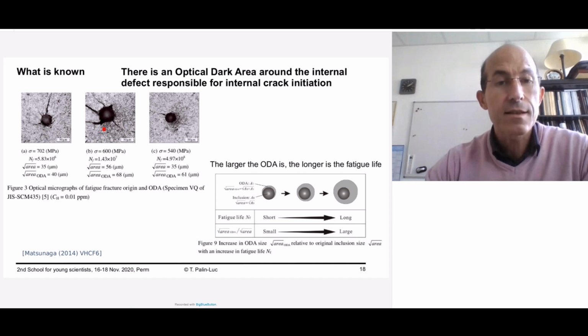And you can see that the area appearing dark around the inclusions increases in size. The square root area of the optical dark area, you can see here, increases from 40 micrometers to 61. This is illustrated also in this schematic picture. When the fatigue life increases because of the stress amplitude reduction, the square root area of the optical dark area increases.